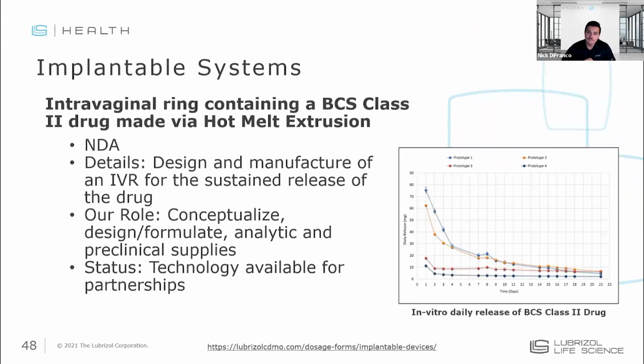We've also done some novel product development as well. So this is an example of an intravaginal ring using a novel design that we developed at our Bethlehem facility, utilizing thermoplastic polyurethanes to control the release of drug from an IVR that has a much higher loading than a traditional intravaginal ring. And so the release data on the right side shows our ability to control the release kinetics from this device in different prototypes.